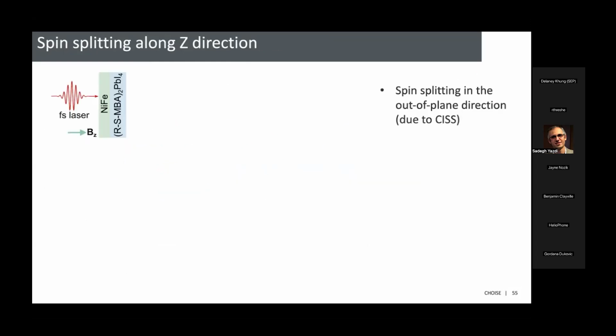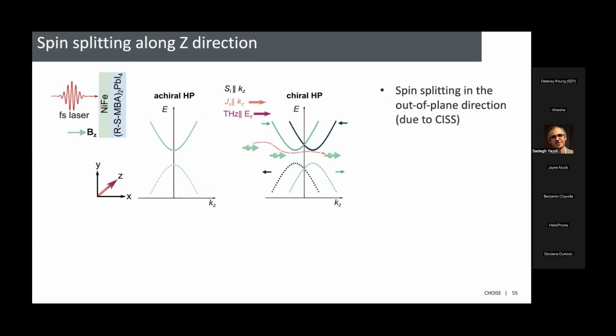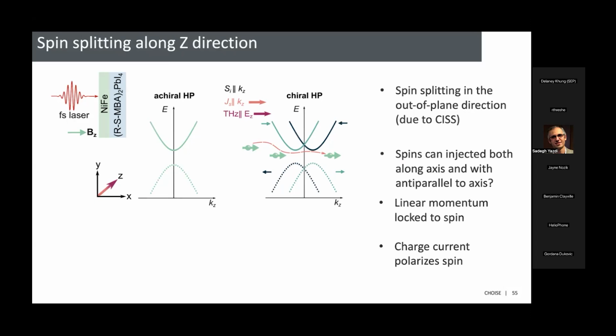Okay, so that's great. What does this mean for CISS anyways? Again, now you have spin splitting in the chiral axis along the z direction. And so now when you put spin along the z axis into the spin split band, it accelerates charge in that direction, and then that's what's measured out. So now if you think about what CISS is doing, you're injecting an unpolarized charge carrier into the spin split band. It experiences an effective magnetic field that polarizes the electrons. All right, so that's what it is. It's a linear momentum velocity spin.